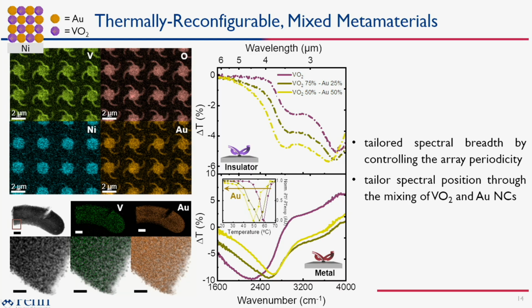And so here we did some EDX to characterize what happens when we mix these materials, and you find the VO2 and the gold intimately mixed throughout the entire structures that we can build. So we can build these out of mixed materials, and what it really allows us to do is control the resonances in these materials. As we add more gold, we shift to higher energy or higher wave numbers. So we can tailor the spectral position simply by mixing compositions of materials to give us new effective building blocks from which to design these.